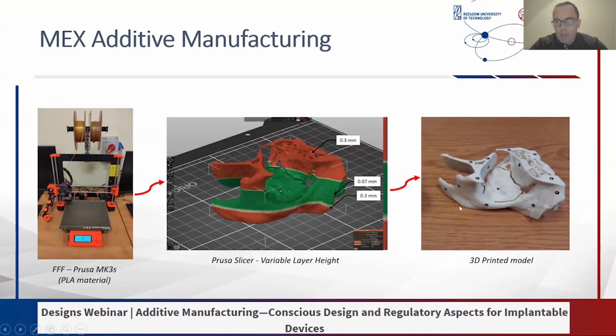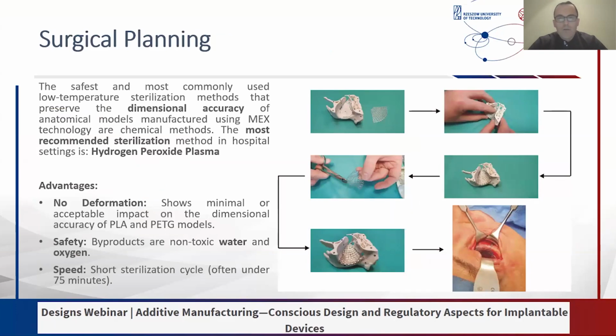So we have one model representing the undamaged part, and on this model there is a cut area of damage. We also have two areas. This area is manufactured using 0.07 millimeters. So we decrease the manufacturing time of the model, because we don't use one uniform layer thickness of 0.07 for all areas. And then we have a 3D model. We choose the appropriate sterilization method.